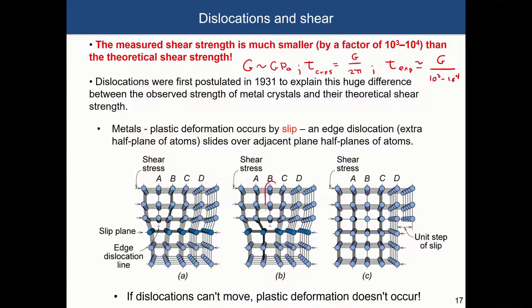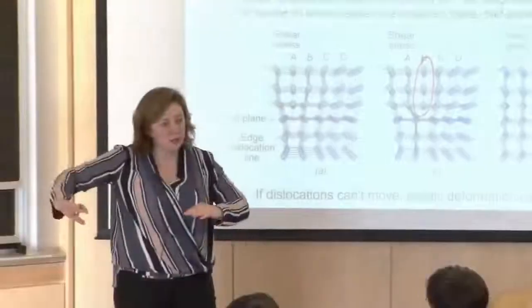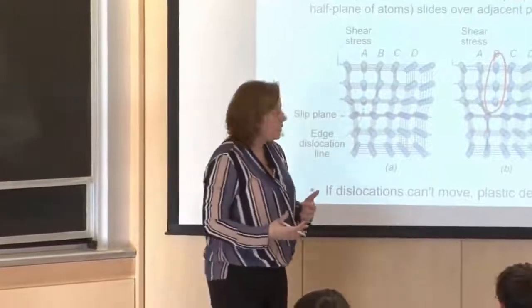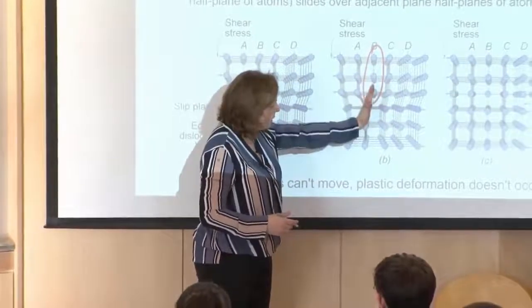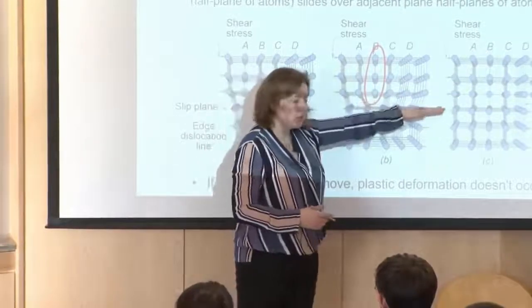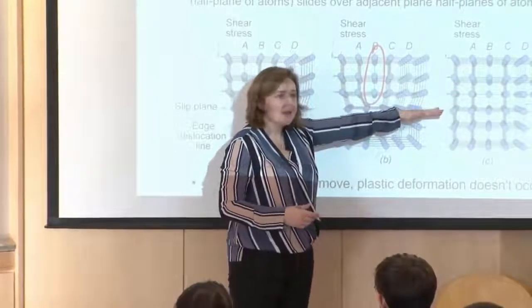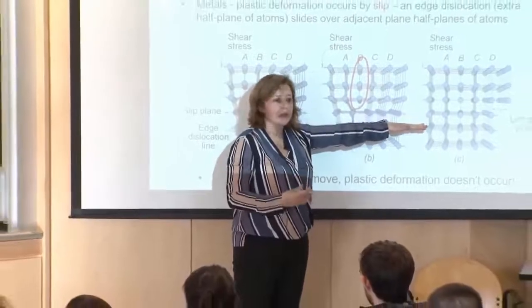what people postulated is that there is a presence of defects called dislocations. In this particular case, it would be an extra plane of atoms that makes this process easier. The stress required to go from the initial stage to plastically deform is not the force required to move all atoms simultaneously, but rather you introduce one particular defect that travels throughout the material, and the stress required for that is significantly lower.